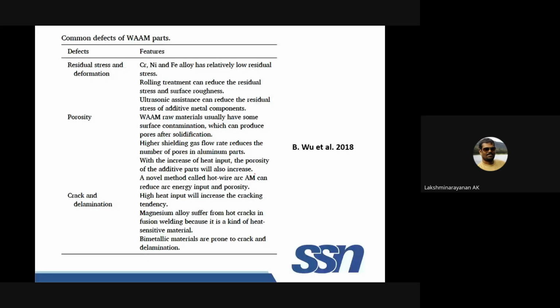So what are the common defects you need to handle? One thing is residual stress and distortion, how it is deformed. Porosity is one of the problems, where if you use sufficient shielding gas, you can avoid that. Cracks and delamination are problems in wire arc additive manufacturing, especially when you deposit one layer and then another continuously. There may be a chance of cracks because of the thermal gradient, so in between you need to have a certain interpass temperature. You have to allow the material to cool down to a certain temperature, then deposit. You have to remember that. Otherwise, delamination most of the time happens here, or sometimes cracks form within the component itself. That is very, very important.